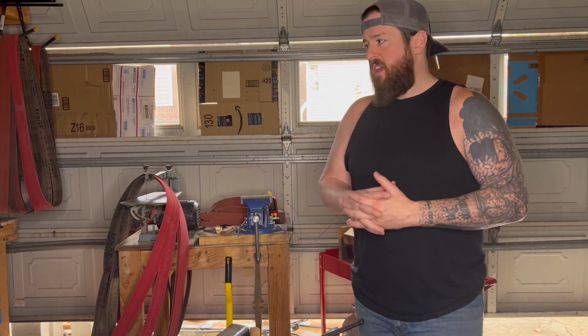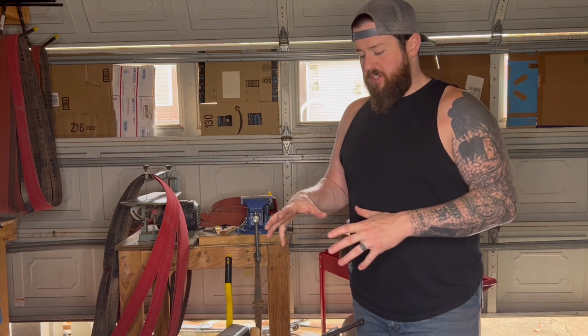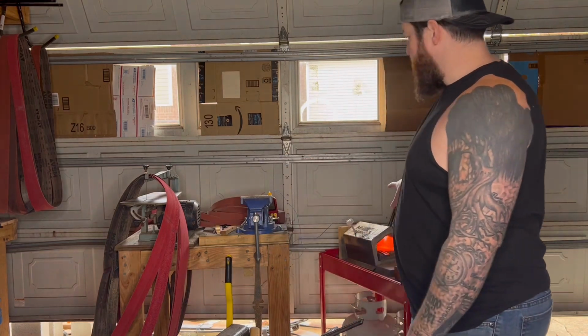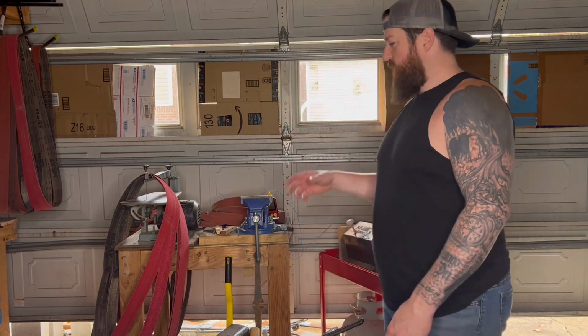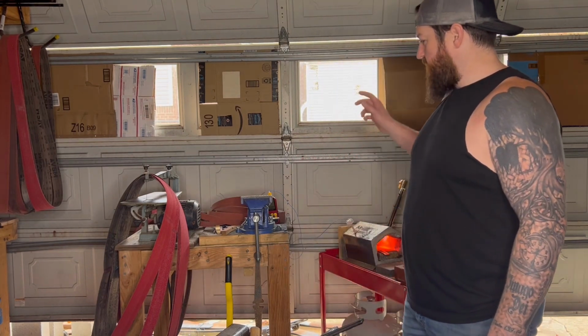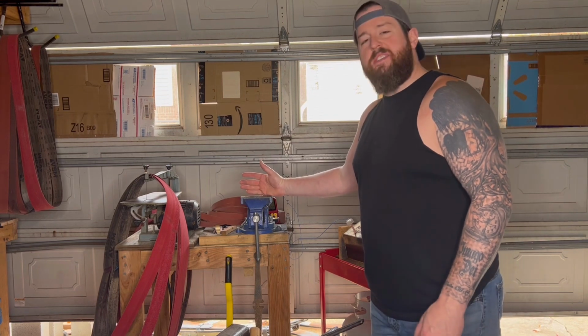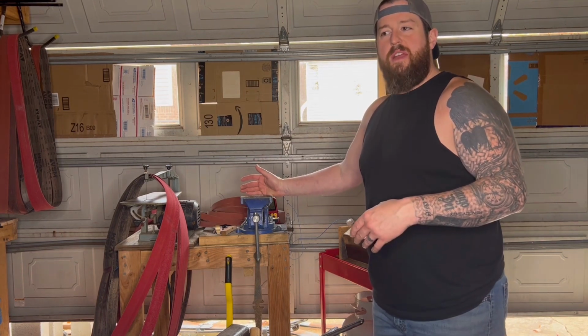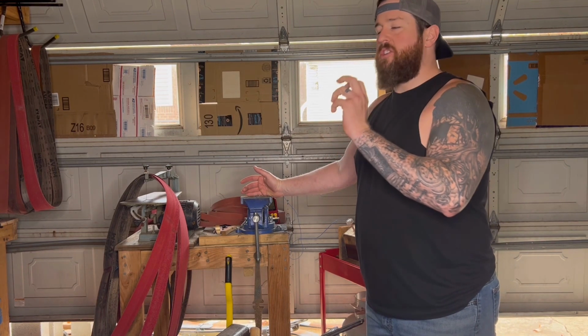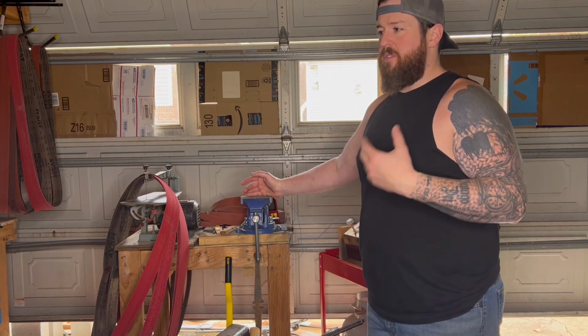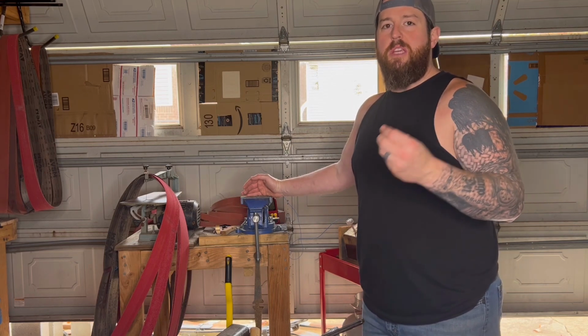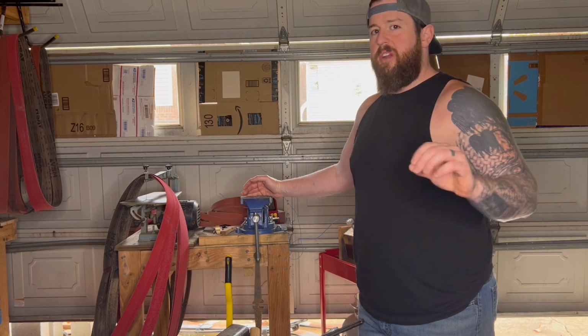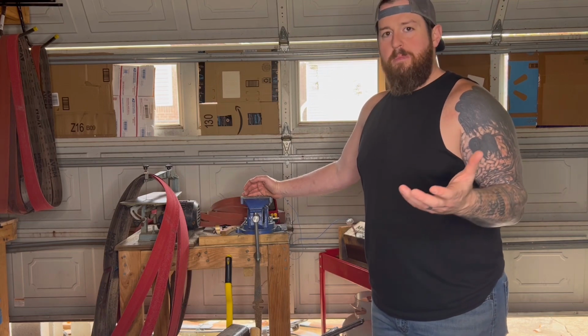It usually takes most of the day. It takes me a few hours of direct hands-on of doing the soak time and everything. So this one's soaking for 15 minutes. The 8670 steel will soak for 10 minutes. Then once it comes out, I'll stick it in the vise to air cool, so it'll cool a little bit faster after this soak. It's just refining the grain of that steel. I do snap tests with all my steel to make sure that I'm heat treating it properly to get a really good refined grain so that I can produce the best knife possible.